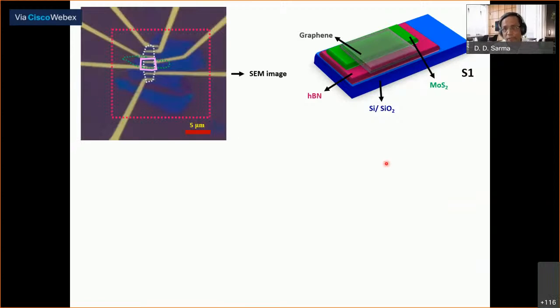Directly looking at the electronic structure, but before that, this is my heterostructure. This is a schematic diagram, looks very beautiful. We can make it look as beautiful depending on how good a graphic software system you have. But when you look at it in AFM, trying to understand what your sample is, this is what you see. This is very nondescript. Actually, this is molybdenum disulfide, and the graphene is sitting like this. There's some more molybdenum disulfide. Oh, this is boron nitride. You can't figure out what is where.